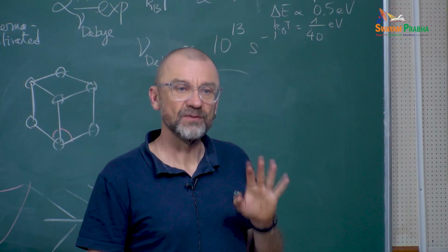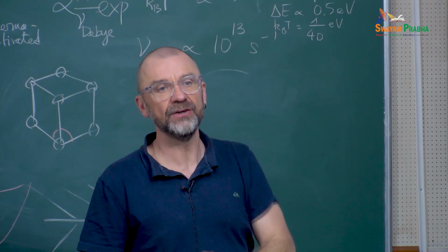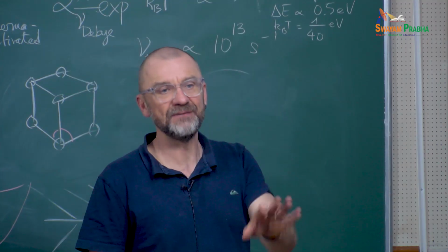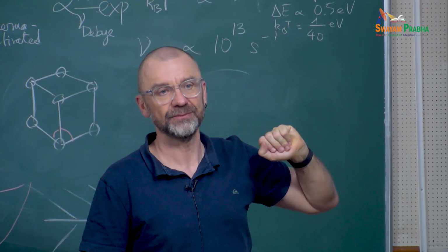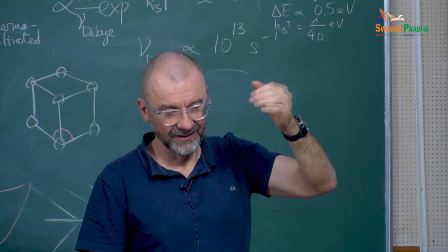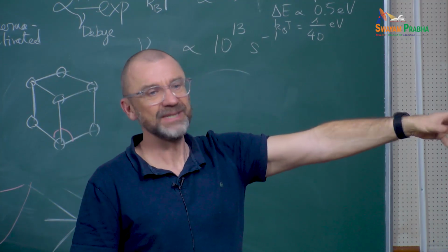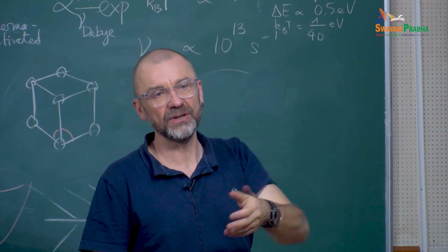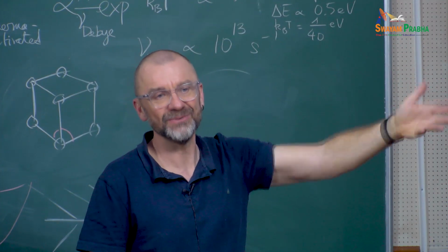Yes, go ahead. For me, extrapolation is if you try to predict the properties of configurations that are not in the training database. For example, you train your potential only on FCC structures, and then you want to look at what your potential says about a BCC structure. This is extrapolation. Our everyday experience shows that with a pair potential, BCC will not be exact, but it will not be completely bad. You take a machine learning potential and it will predict that the BCC phase, for example, is completely unstable, whereas we know it is metastable.